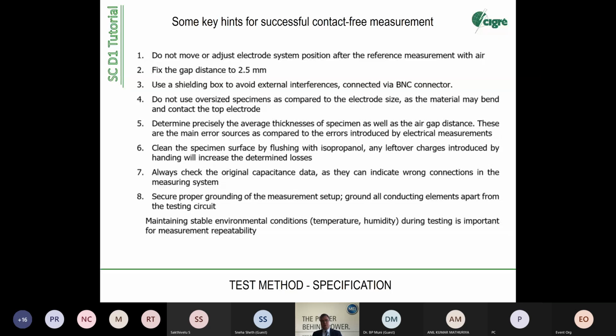Sometimes you say, okay, my measuring area is 100 millimeter diameter. Take a big plate and put it under the electrode. Don't do it because it affects the factor K because of the stray field. Determine precisely the average thickness of the specimen as well as the air gap. As I mentioned before, these are the main error modes or error contributors. Clean the specimen. Always check original capacitance data.